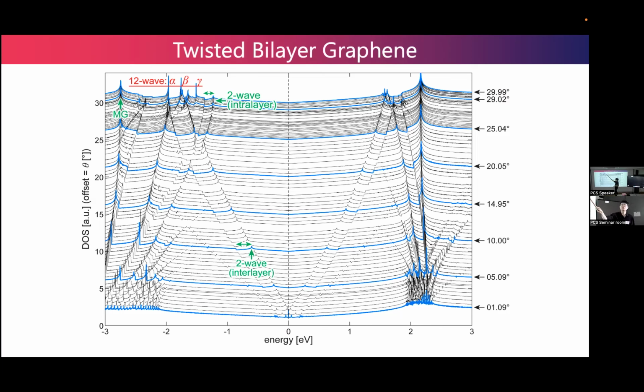This is the band opening by intralayer interaction, which couples two states in the same layer, assisted by the scattering mechanism in another layer. Actually, intralayer coupling also exists in low-angle twisted bilayer graphene, but it becomes prominent only in higher-angle structures. Finally, this very sharp peak is prominent only in the very close vicinity of 30 degrees. That actually turned out to be the quasicrystalline resonant states.